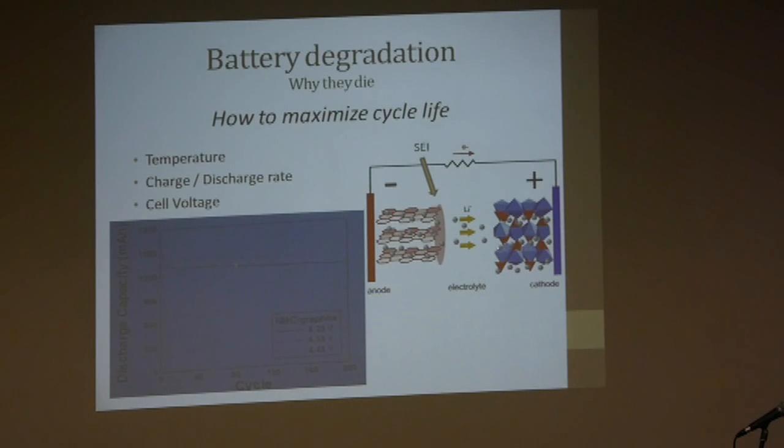And that's because at these higher voltages, you can see voltage as a sort of pressure to push these ions between those sheets of carbon. And it can actually pulverize those carbon sheets. And then they do not make an electrical contact with the anode anymore, and they just don't participate in being a battery anymore.